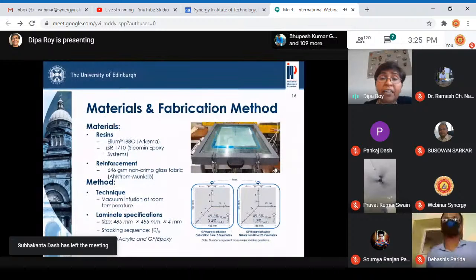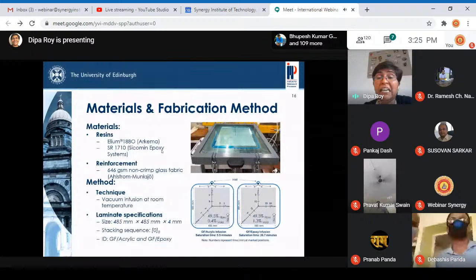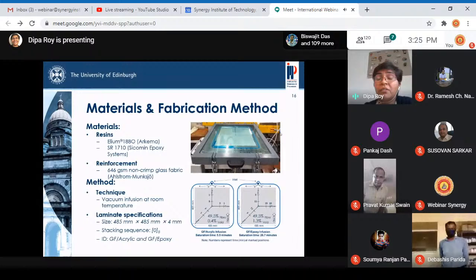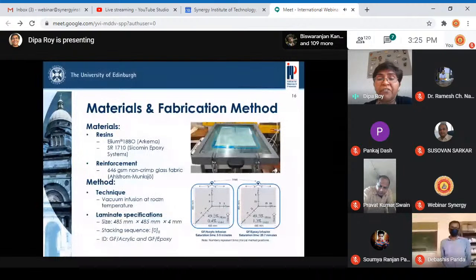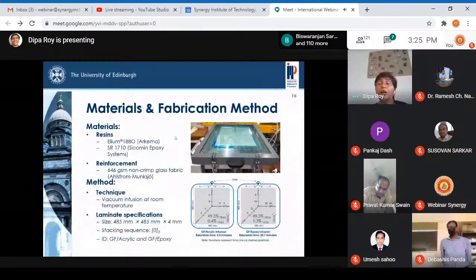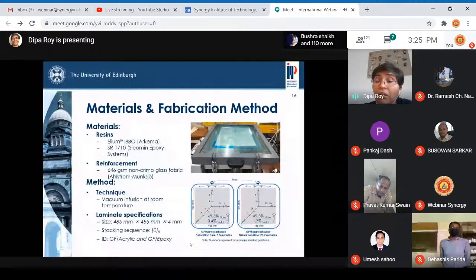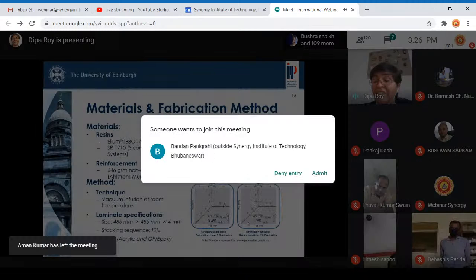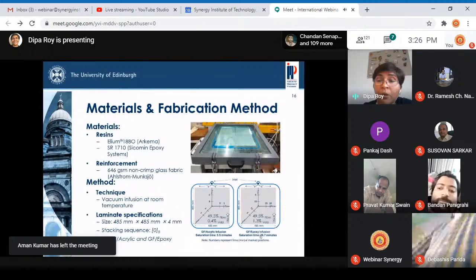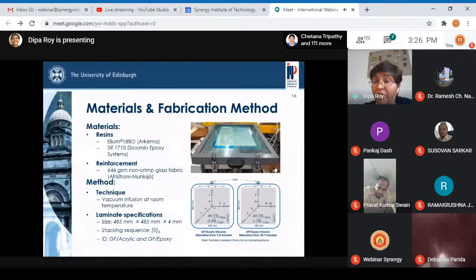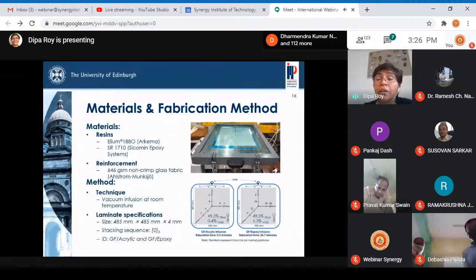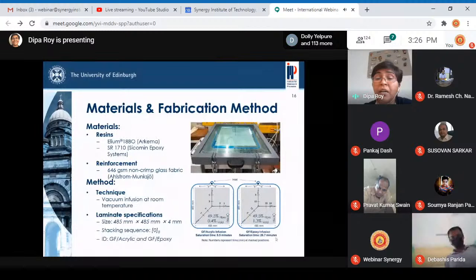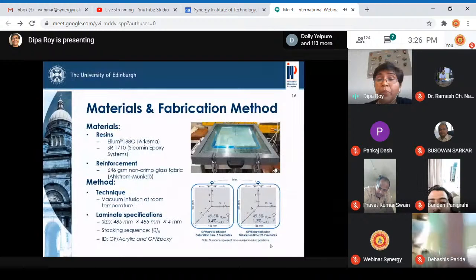We used this acrylic resin from Arkema, and we used epoxy resin, which is a standard epoxy. We manufactured two laminates, very similar, keeping everything the same: the glass fibers, the layup, number of layers, layup sequence, and the matrix or resin. In the case of the epoxy composite, the total filling time for the mold was about 27 minutes, which is quite standard with any standard epoxy resin. Whereas with this acrylic, the main reason is its very low viscosity. It flows really fast, the overall impregnation is very quick, and the manufacturing can happen in a much shorter time. Since everything was done in a very similar way, we did a comparison, and there was a clear advantage of using this kind of thermoplastic resin.